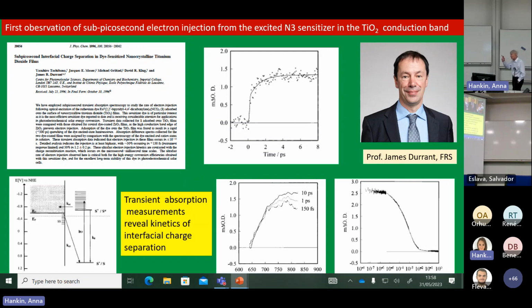First of all, the question is how to get the charge separated. It's an interfacial reaction, and so the electron can go in but can also come back out of the TiO2 to recombine with the dye. What the studies that he published with James, almost 30 or more years ago, showed is that there was a large difference. Injection, this is actually the same ruthenium complex I just showed you, was measured. The reaction is over in a couple of picoseconds, and you can see most of it actually in the femtosecond range. But then the recombination of the electron with the dye, the recapturing of the electron by the oxide side, is many orders of magnitude slower. You're talking here microseconds to milliseconds. So you have 8 orders of magnitude.